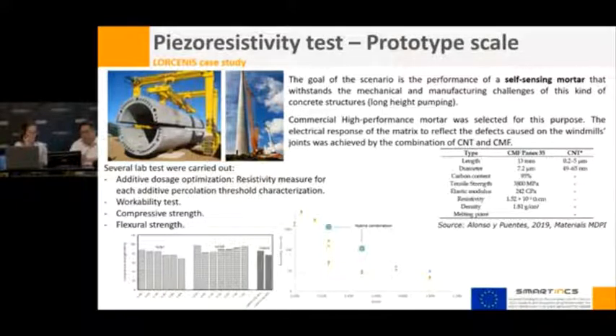In our case, we chose a commercial high performance mortar, one from the Sika brand. To improve the electrical response, we use a combination of carbon nanotubes and carbon microfibers. The properties are here. The carbon nanotubes were multi-walled ones. And for the characterization of those dosages, several lab tests were carried out. The first one, dosage optimization: we performed resistivity measures to determine the percolation threshold, as we saw before.